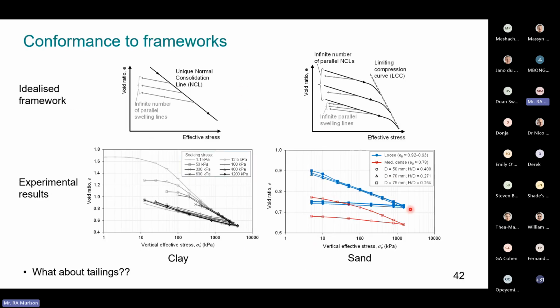So in summary, we've got our sand results here where we've only considered the medium dense test where H/D was sufficiently minimized, and then we look at our three loose tests. And here we have parallel normal consolidation lines. So it behaves like the idealized framework for clean sands. And as discussed as well, we've got results on a clay which conform to the idealized framework for clays.